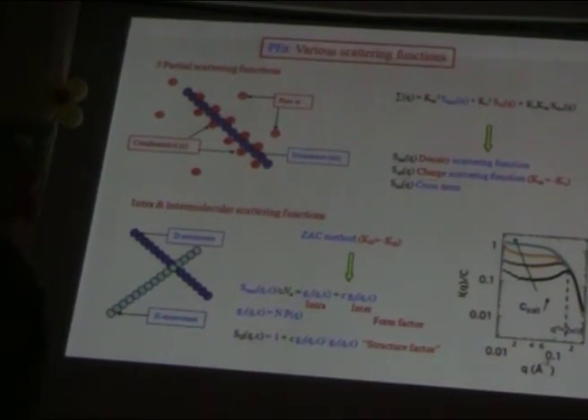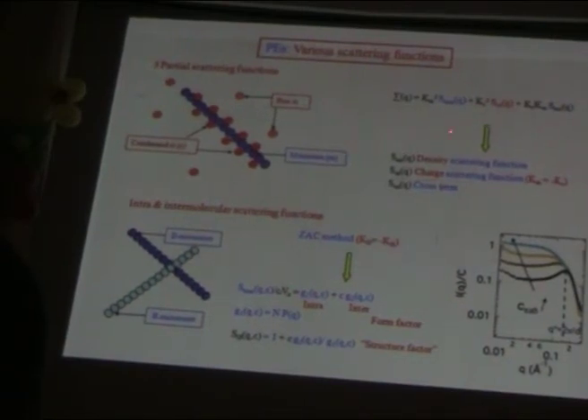Okay? From these partial scattering functions, depending on the technique that you use, you will see mainly, for example, the macroion. That is the case if you use small angle neutron scattering. But if you use small angle X-ray scattering, you will see both the macroion but also the counterions. With small angle neutron scattering, you can also use the contrast variation method, which is very easy. You use labeling by replacing hydrogen atoms by deuterium to change the contrast length of the macroion with respect to the solvent, or the contrast length of the counterions with respect to the solvent. If you use the deuterated macroion in D2O, and also hydrogenated counterions, you have a chance to observe only the counterions.